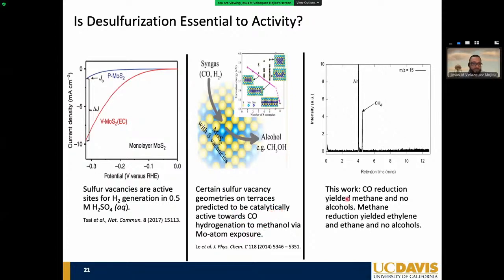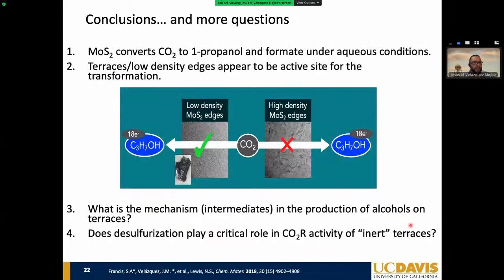methanol. And also we did a little bit of work changing the target molecule, so basically doing CO reduction and also methane reduction. And indeed we're seeing what could potentially be some interesting product formation from CO2. So for this part of my talk, there is a lot more to do, of course. We're figuring out ways to perhaps control monolayer growth over a centimeter square of molybdenum disulfide that we could then deposit on a conductive substrate and have a deconvoluted way for us to control the surface motif. So just like I showed in that initial little table, have vacancies or not, or have edge sites or not.